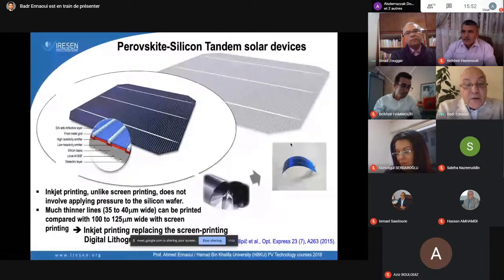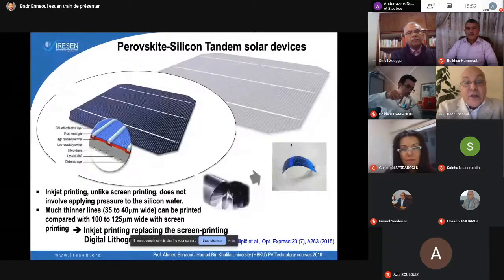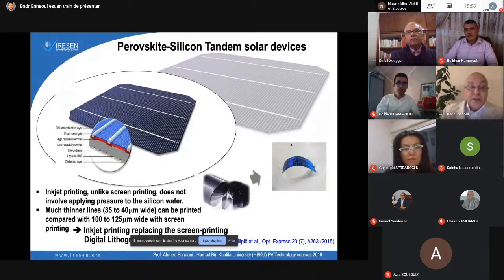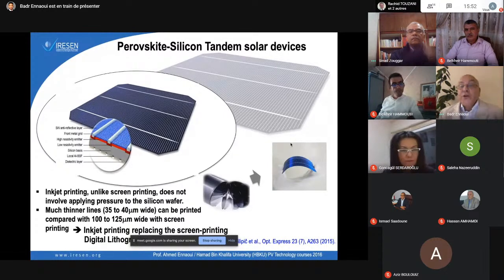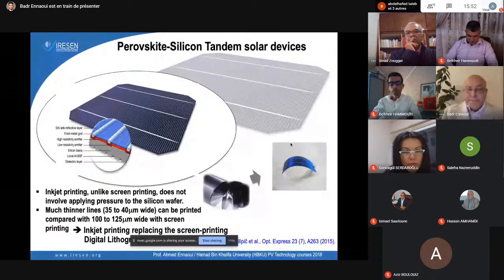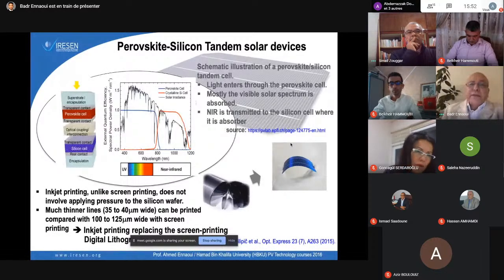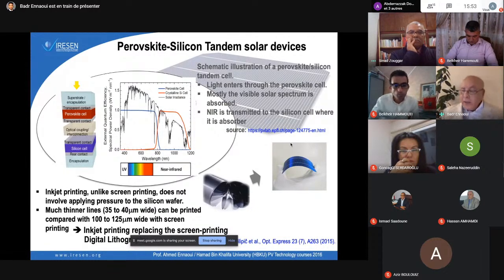With screen printing, you can get 100 to 125 micrometers. And we are talking about large scale facilities. So if in every solar cell you lose 1 square centimeter, on terawatt scale you can lose a lot, and therefore this method is very important. So for making tandem solar cells between silicon and perovskite, inkjet printing is very important. You can have your silicon solar cell, and you can use inkjet printing to print the perovskite. There is a company in England, I think in Oxford, doing this kind of inkjet printing of perovskite.